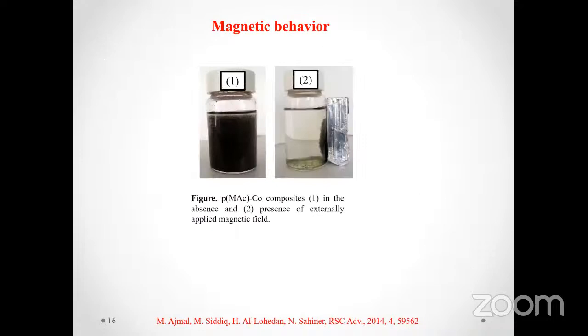And here is the magnetic behavior of these composites containing cobalt nanoparticles. When cobalt nanoparticles, which are magnetic in nature, are prepared in a hydrogel system, then the overall cobalt hydrogel composite system becomes a magnetic system. And this magnetic property provides an advantage to control the catalytic activity of the system by applying an external magnetic field during the reaction.